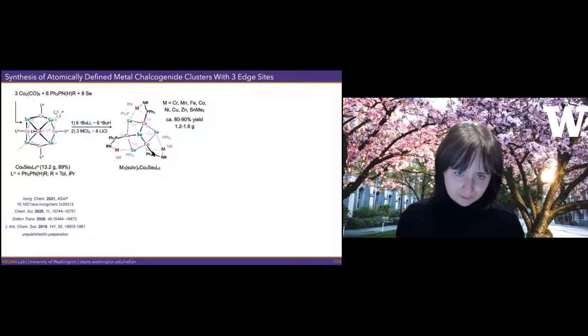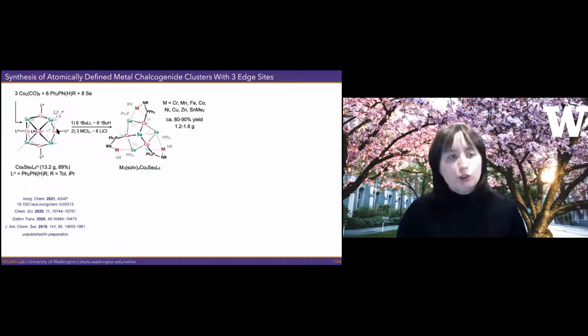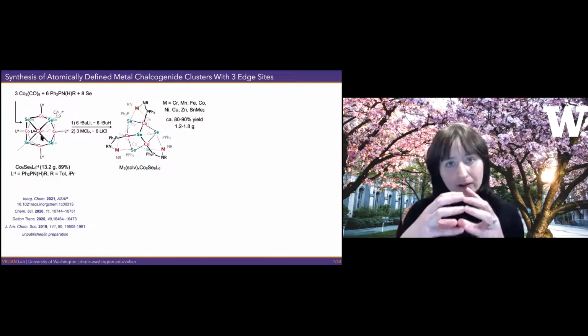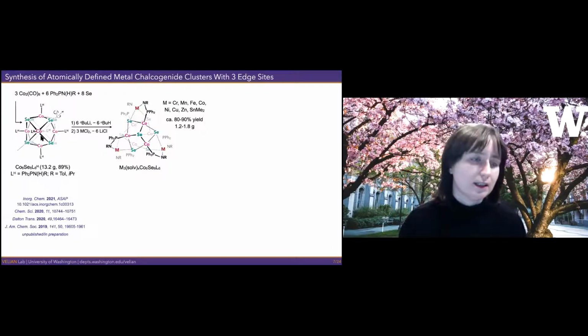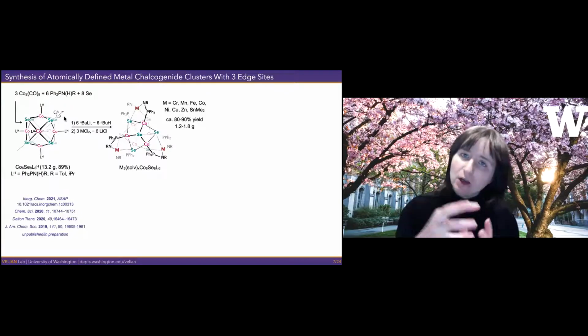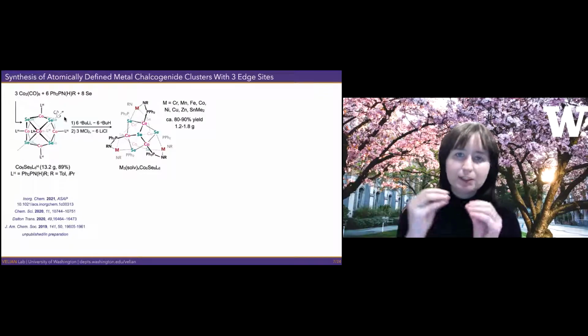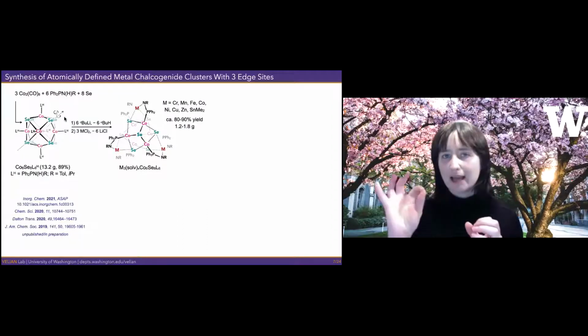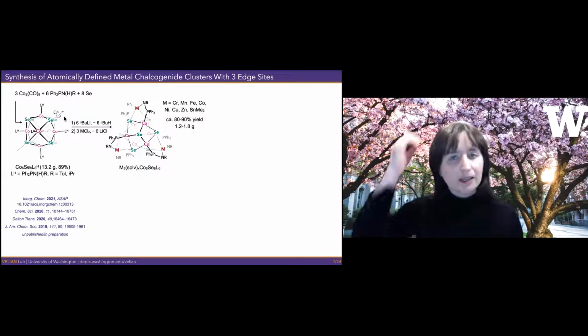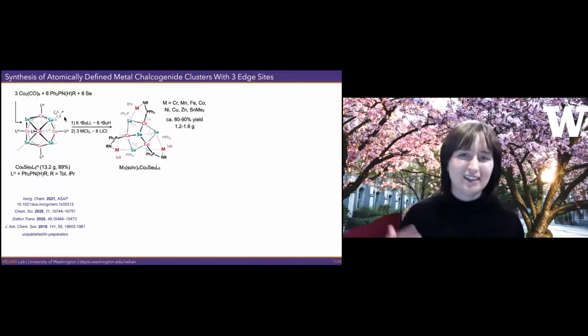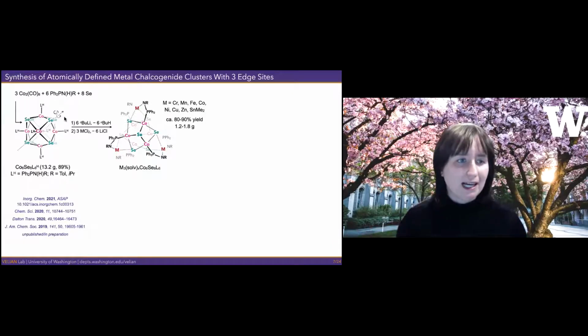projected here, okay? But what we thought we would do is use this as our core, kind of analogous to that molybdenum sulfur flake, and then use capping ligands to provide a surface coordination site for a different kind of metal. And then we can have, in a very controlled environment, this interaction between the support, the cobalt selenide, and the surface side that is there to interact with the core and see how that compares with this heterogeneous catalyst that I was describing earlier.